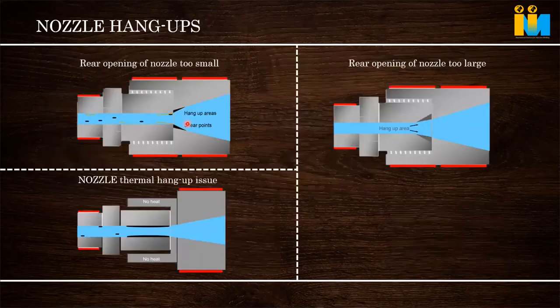See, the nozzle diameter we have to maintain properly. Second, the inside area. If you see a machine nozzle, or a second spare nozzle, they will machine the outside area very nicely, with lathe and all, then afterwards smooth polishing, and it looks very nice. But if we see inside the nozzle, it will be just drilled. They never polish it properly or remove the cutter marks inside the machining area. Every spare nozzle has this problem. So the inside area of the nozzle ideally has to have all the cutter marks removed.